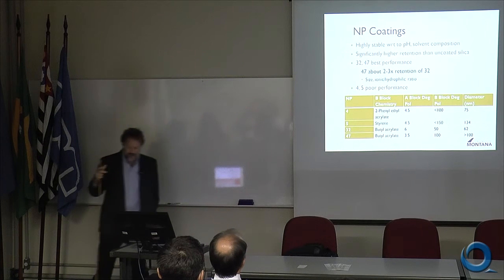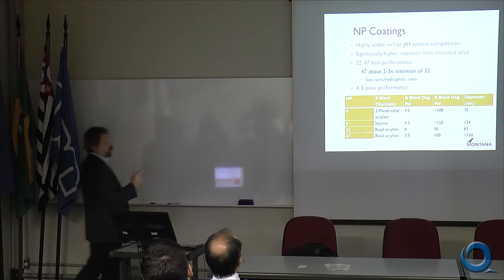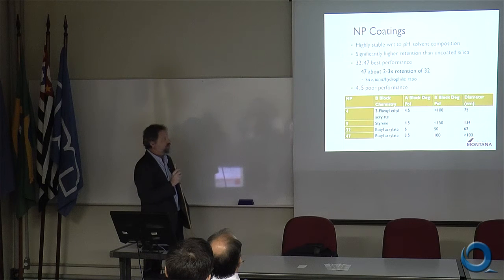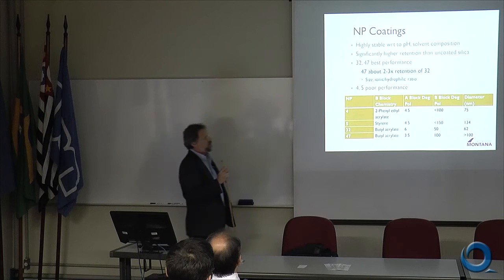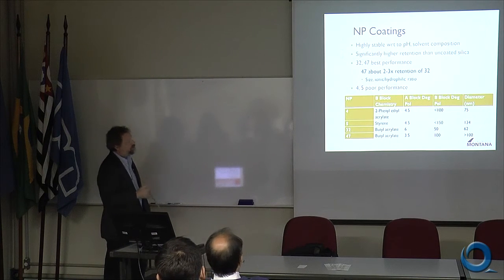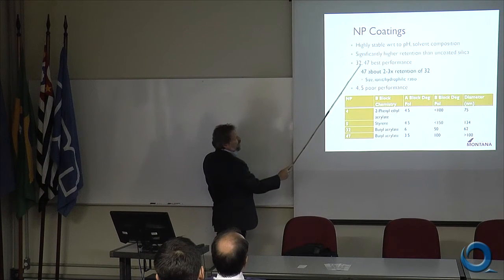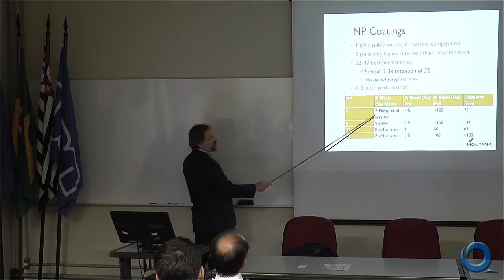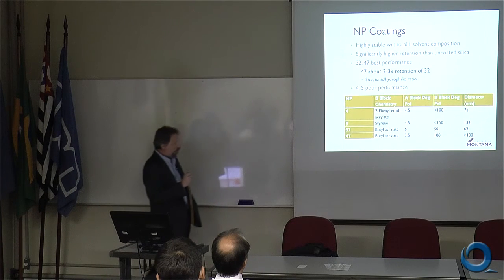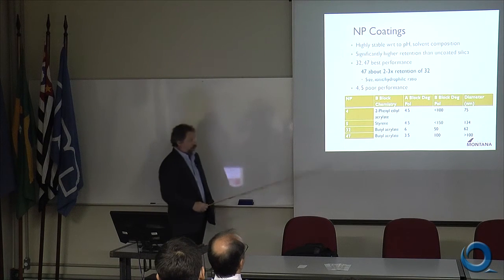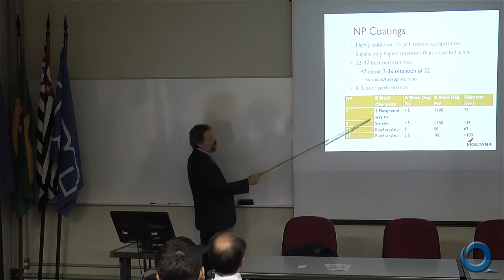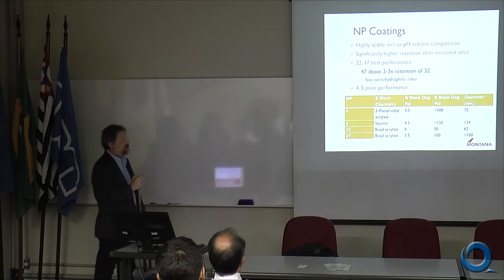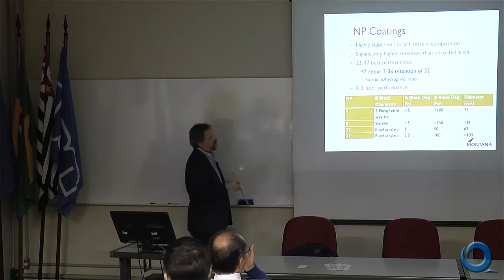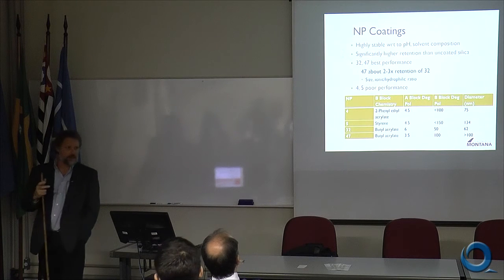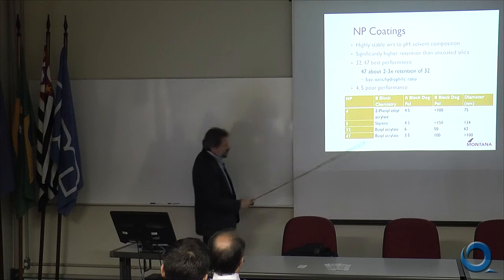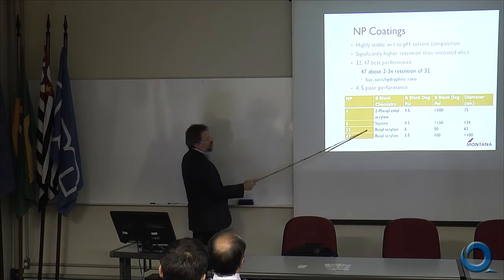So that's really good news. We also, of course, went and did the experiments where we ran our retention experiments with bare silica without any nanoparticles on the silica. And the nanoparticles do have a significant effect. So what we're seeing in terms of retention is really retention caused by the modification by the nanoparticles on the surface. We've done almost all of our work with these two nanoparticles, these two butyl acrylate nanoparticles, because when we tried to do some experiments with the aromatic nanoparticles, we got very poor performance. We don't know yet why that might be the case. I think that part of the problem is that these were very difficult to synthesize, and so what I brought with me were low concentration solutions at less than 1% nanoparticle in solution. So we're not modifying the silica surface with an 8% solution the way we are with the other nanoparticles. So that may be part of the problem. In any case, all of our usable results came with these two nanoparticles.